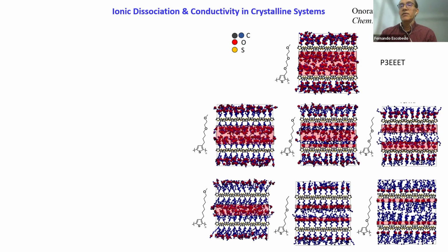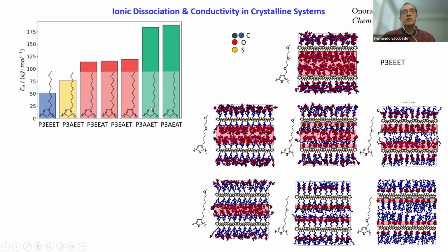Well, if I were to do the same thing for the other chemistries, you see that these red regions are smaller and less connected. And if I were to ask you, just based on these diagrams, which material would seem to be the best at solvating the salt? Probably most of you will say the first one, right? Because you have a larger region of oxygen, so it should be easier for these ions to find this interaction with oxygens to dissociate. And you will be right.